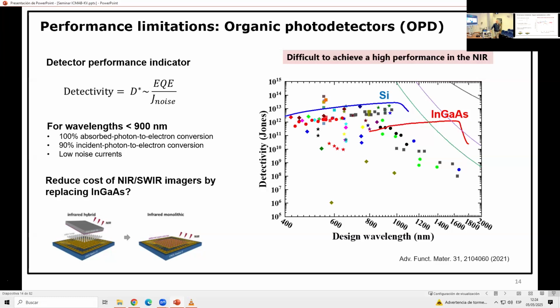So that's the number. Well, maybe that's why I put this graph here. Silicon, and it looks a bit like the absorption spectrum of silicon. Silicon reaches at room temperature, this figure of merit, the important number, is about 10 to the 13 Jones.